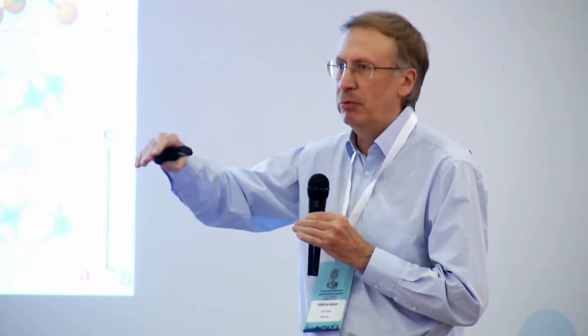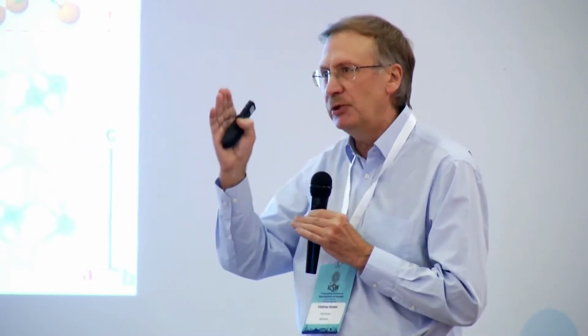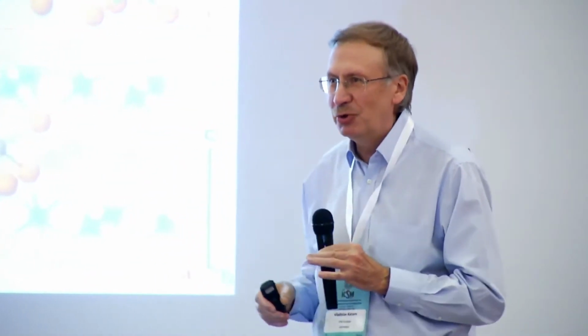What is established now very well is that this two-dimensional magnetic layer is actually a ferromagnetic layer with all moments of manganese ions parallel. So they're all happy, they're not frustrated. And there is also a stronger or weaker interlayer interaction, which is antiferromagnetic. So in zero magnetic field the sublattices are antiparallel, collinear, and there is no conflict of interest, so to say, which is usually the case in frustrated magnets.